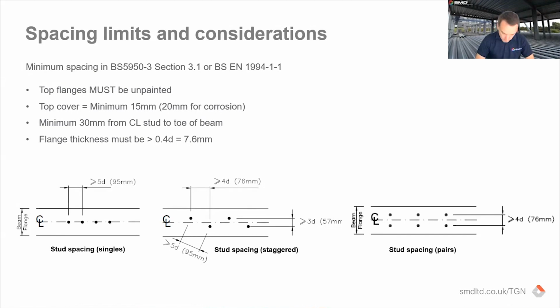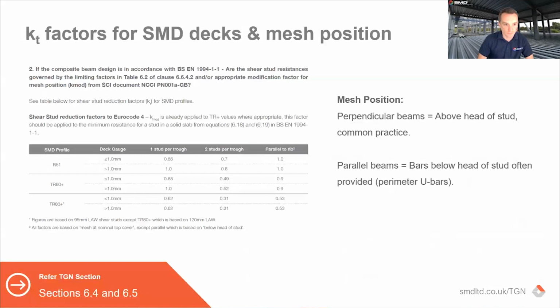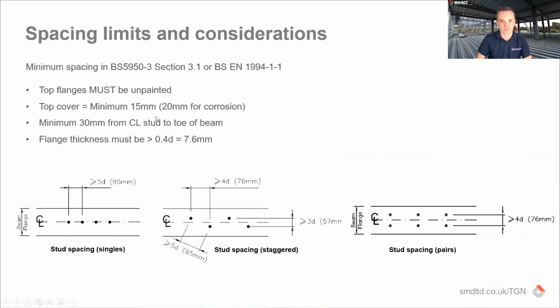Yep. And the question is, does this mean that the increase in capacity can come from increasing deck thickness and concrete class? The increase in stud capacity, yes, there is an increase. If I zip forward again, you can see here the increase for deck thickness is incorporated in the factors. So you can see once you get above 1 millimeter, the factors do change. So with certain profiles, it all comes down to the equation. But principally the answer to that question is yes.